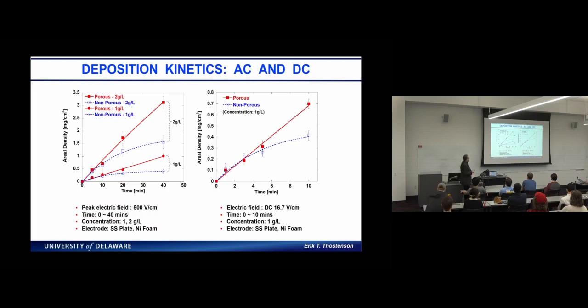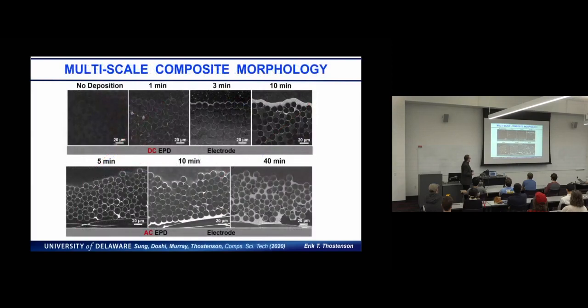This is where we've been doing it for longer because we want to get more material in there to increase the mechanical properties, but we don't have to add much for electrical properties. So what you see here, just a couple of minutes, you see these bright rings. This is a gallium ion microscope image, so the bright rings are conducting area. Where we don't have anything deposited, this is a glass fabric, I believe, you don't see anything. But you see, very quickly, this conducting network form. And that's what enables our work in sensing.